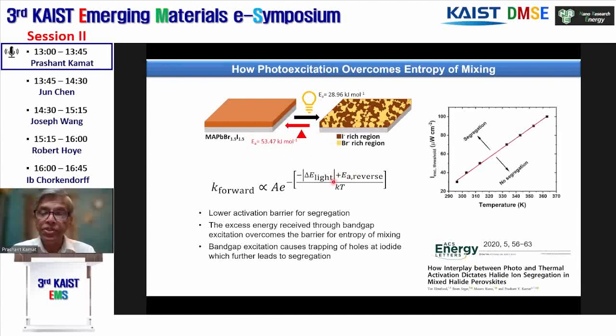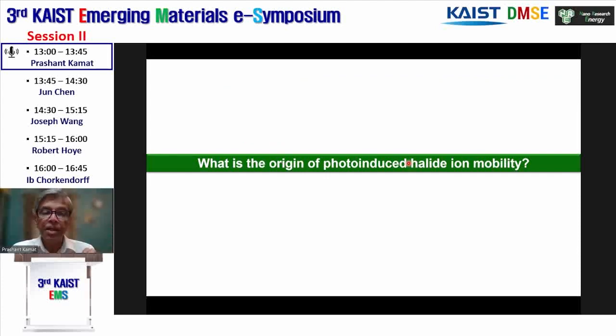So as a result, what we see is a threshold energy for each temperature. And here it is. So with increasing temperature, we need more light energy, because otherwise the driving force also increases for the mixing. So again, this summarizes both the dark mixing versus light-induced segregation. Okay, so this is a property, again, associated with the halide ion migration. So now the question is, what is the origin of this photo-induced halide ion mobility?